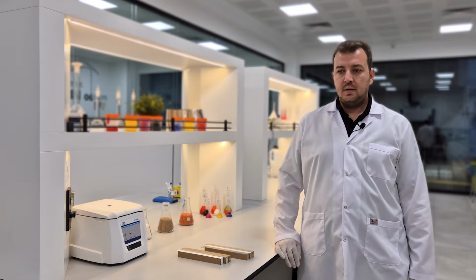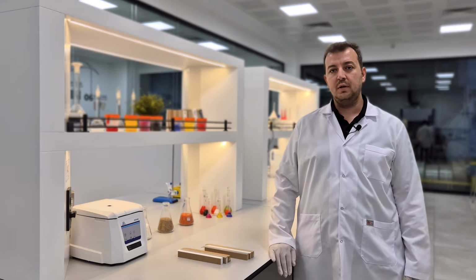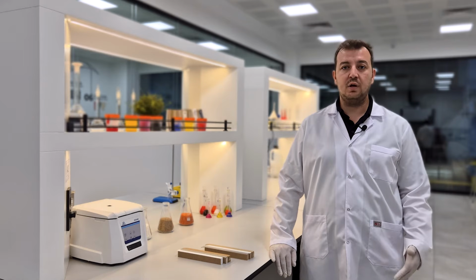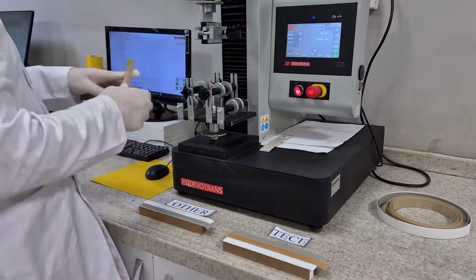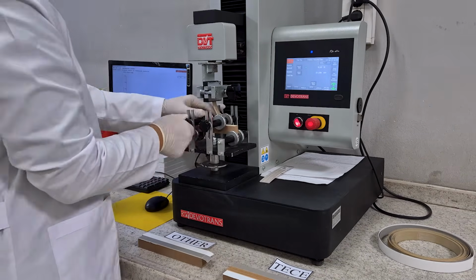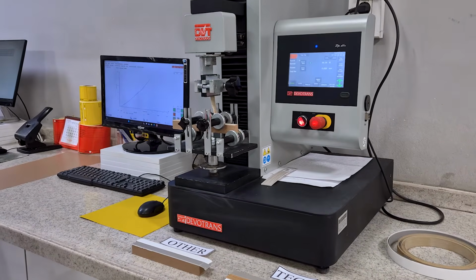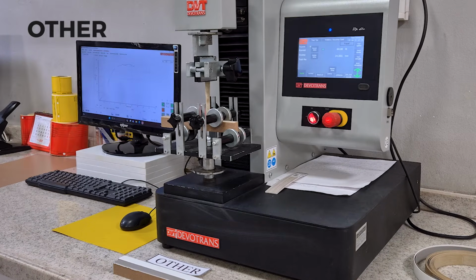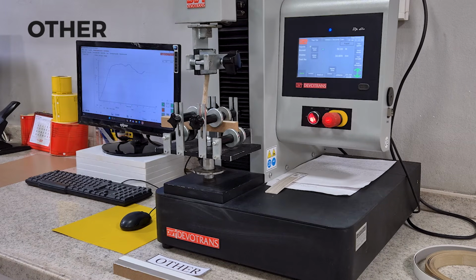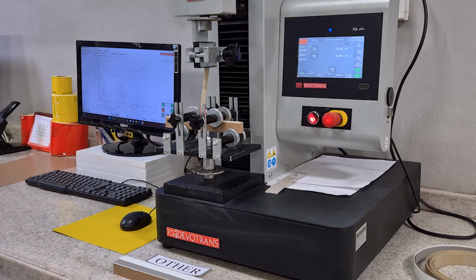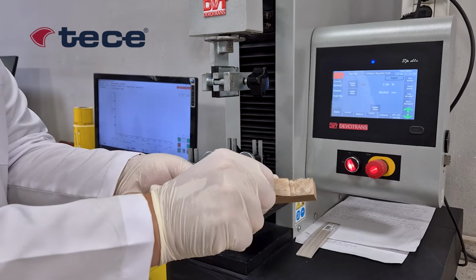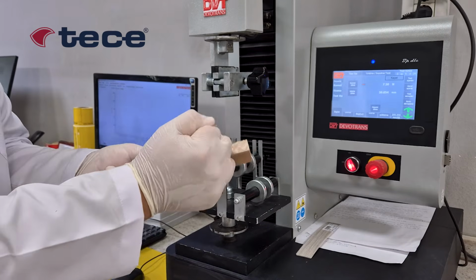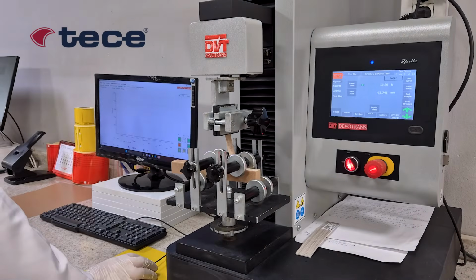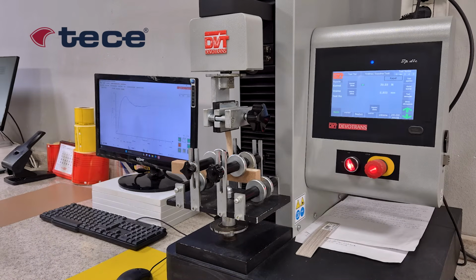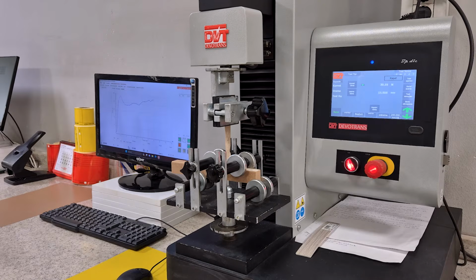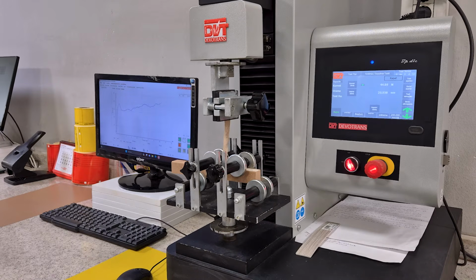In our test, both the cheap products and the Tece products were applied to MDF using the same machine and the same adhesive. After resting for 24 hours, we test their peeling resistance with a device. The other cheap edge banding shows very low peeling resistance due to very little primer, and almost comes off the surface on its own. Our Tece product remains fully bonded to the surface. The difference is clear, almost twice as strong. Quality primer means longevity. Over time, with heat, humidity, and stress, this difference becomes even more apparent. Our product holds on and doesn't let go.